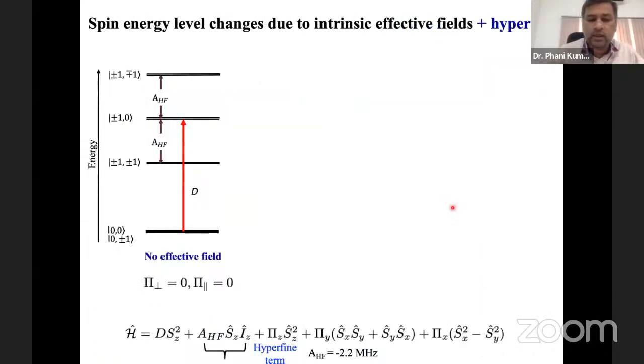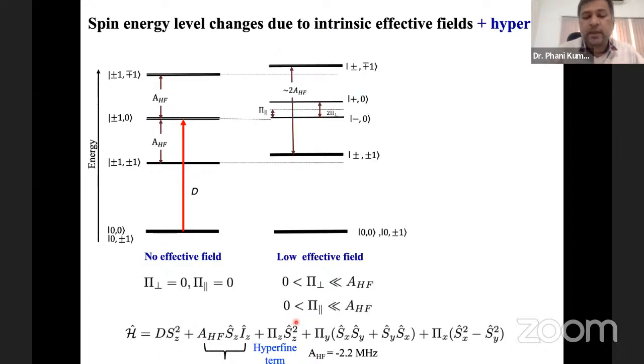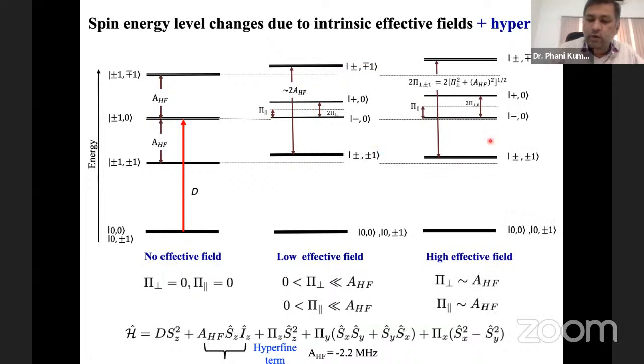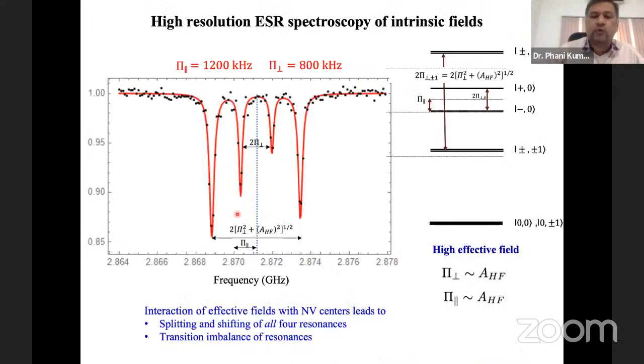But now if we have this zero field splitting, hyperfine term, and then the effective field term, typically most of the samples have very small effective fields. In such a case, only the central resonances get split and shifted, but the outer resonances are not perturbed. But in our case, what we have noticed is that because these samples have very high stress, on the order of the hyperfine interaction, we see a widening of the gap between the two outer resonances also. In this way, we can understand how this spectrum is modified because of the presence of a very large effective field, which has not been observed until now.